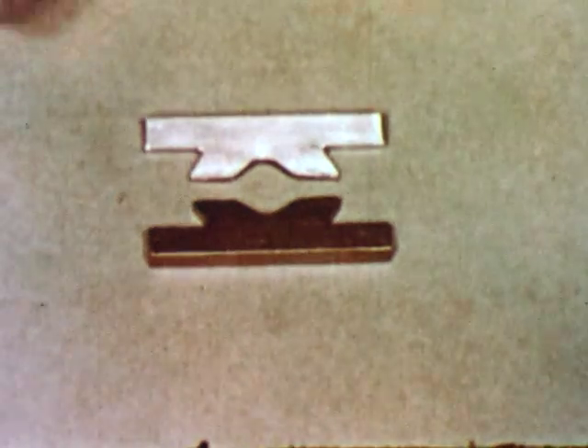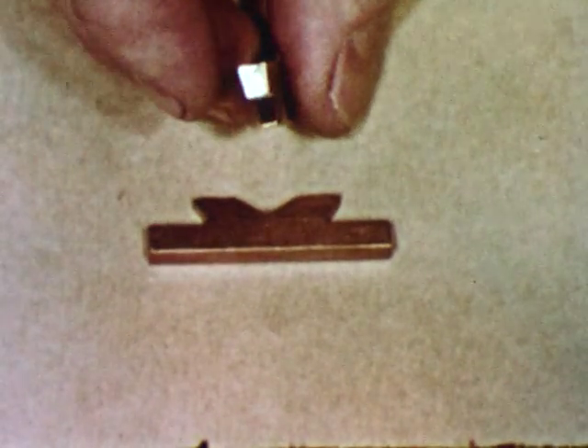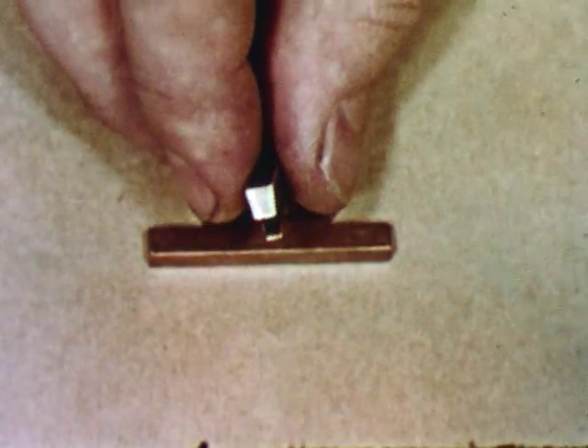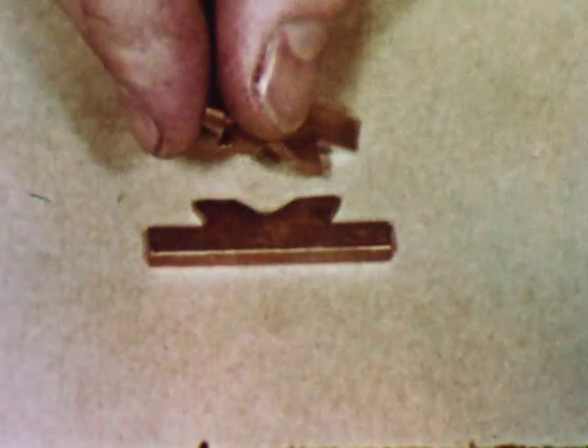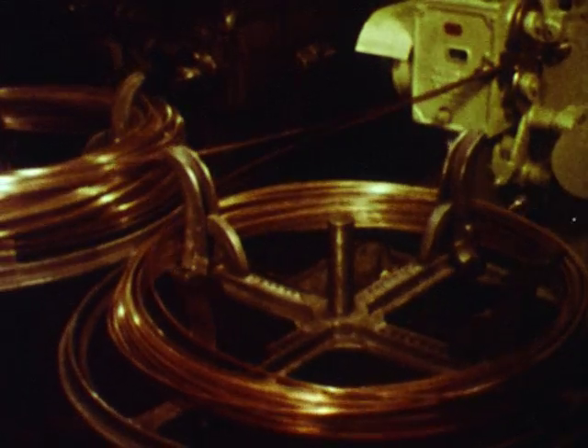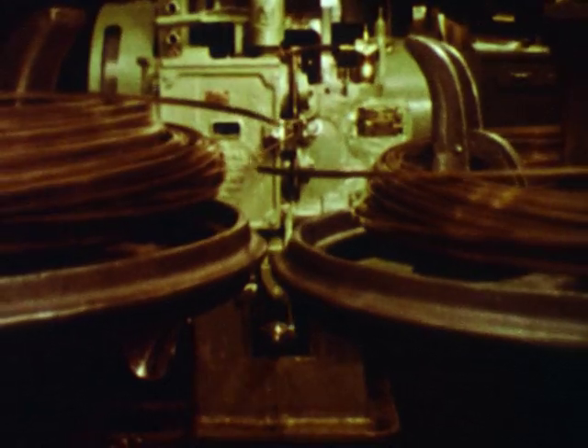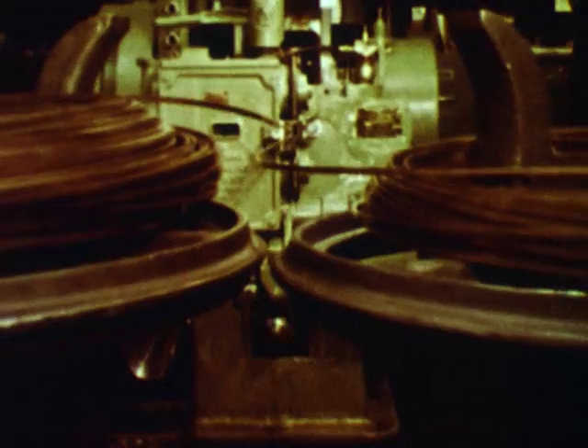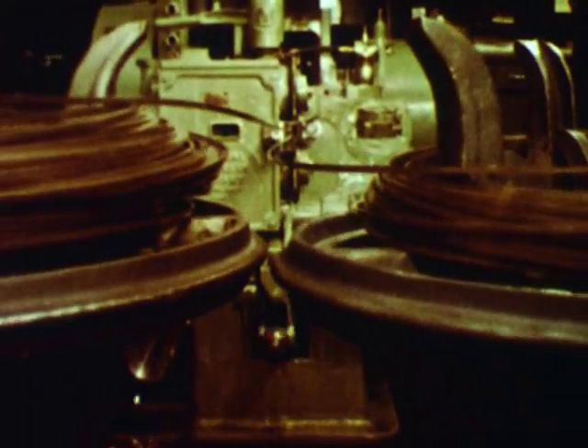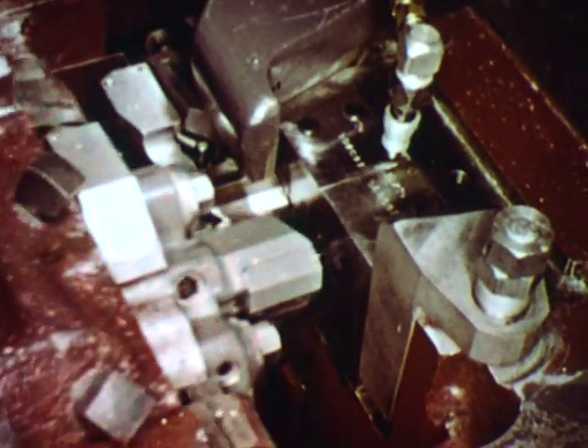Commutator bars are made on a 1/4 inch cold header, 2 at a time, at 240 per minute. Preformed copper wire, wedge-shaped, feeds in 2 strands at a time. 2 of these headers save one manufacturer more than $30,000 a month in material alone. A special cutter shears and transfers the blanks to the die.